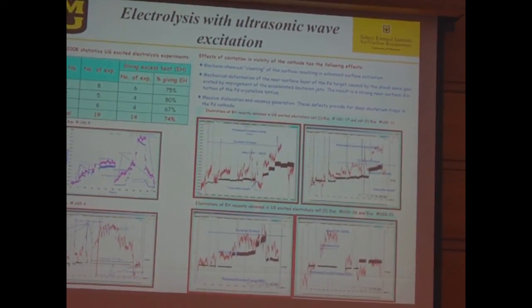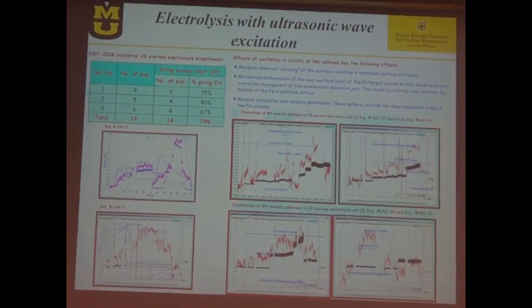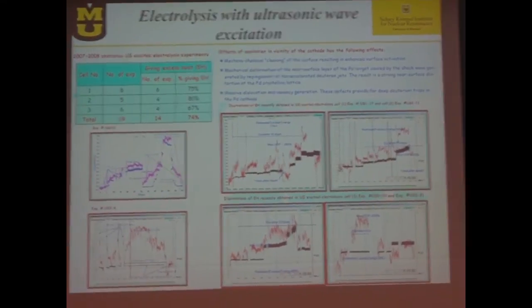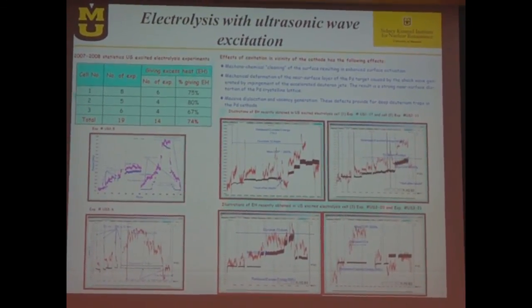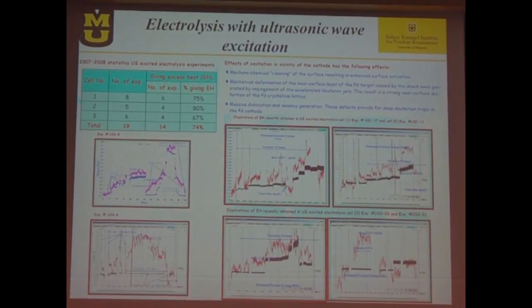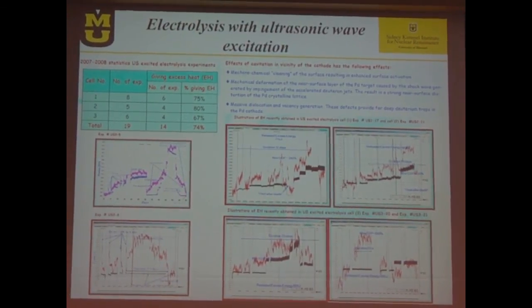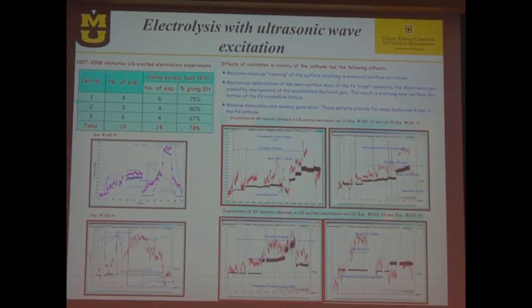What is important when you are using ultrasound excitation, and especially ultrasound excitation with power level which creates cavitation? Cavitation, collapse of bubble, jets of deuterium impinging the cathode and actually deforming the cathode and creating dislocations, creating defects, creating deep traps within the bulk of the cathode, and that allows to increase the absorptivity of deuterium into the cathode. So, first of all, ultrasound is cleaning the cathode, and you know that electrochemical processes are introducing a lot of contaminants on the cathode. So ultrasound is cleaning and making the cathode more active and ready to get the excitation and to start the process.